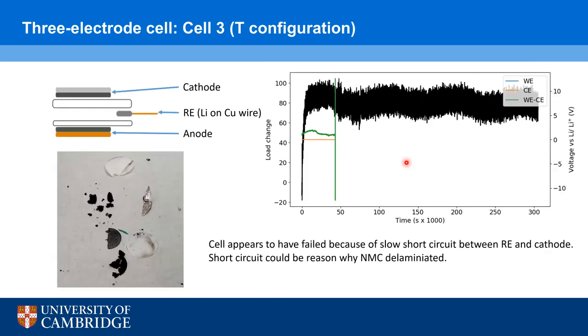Yeah, and then on the third test, we again went back to this T cell configuration, and again unfortunately had a short circuit. This time it was a slow short circuit. Looking at the counter electrode, the NMC cathode, we saw that there was a slow short circuit, and upon opening the cell, the NMC cathode had delaminated from its aluminium current collector. We believe that was because of the short circuit. But again, we still saw this slight increase in the pressure as the binder swelled and this native SEI formed.